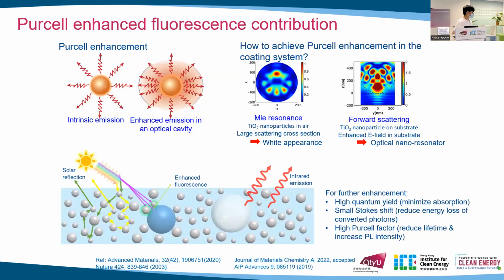But actually, we did not know exactly how this enhancement occurred. Because we see the PL lifetime reduction, which is generally seen in Purcell enhancement phenomena. That traditionally happens to a quantum emitter. A single point emitter has its intrinsic emission, while if we put this emitter into an optical cavity, the dielectric environment is changed, and the spontaneous emission rate will be increased. So the emission intensity will be increased. But how does this Purcell enhancement occur in this coating system?